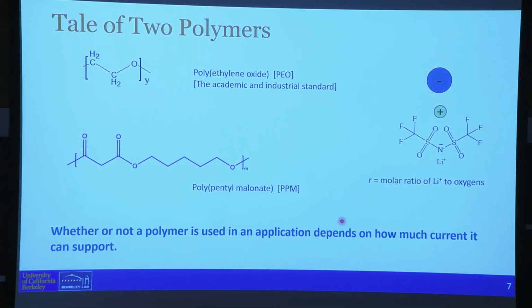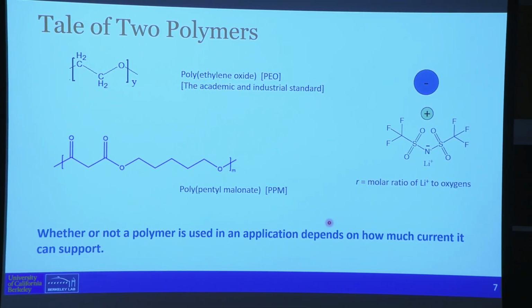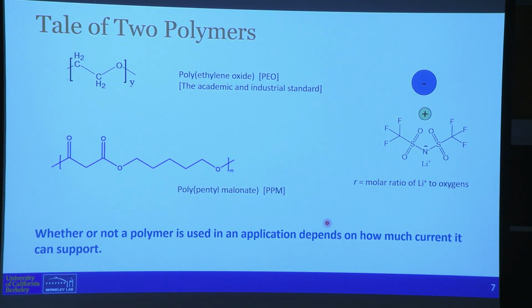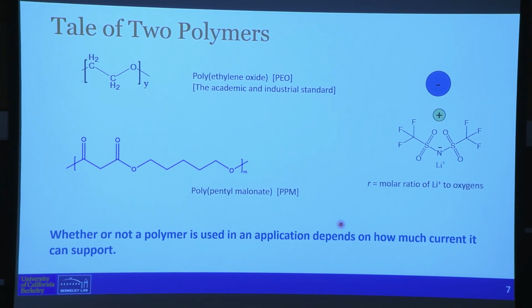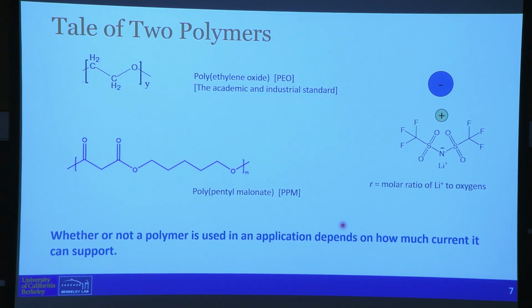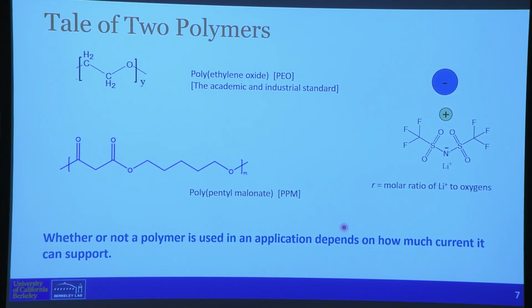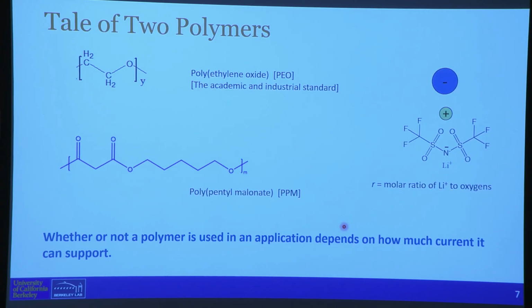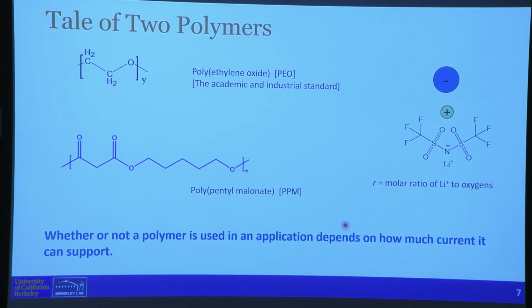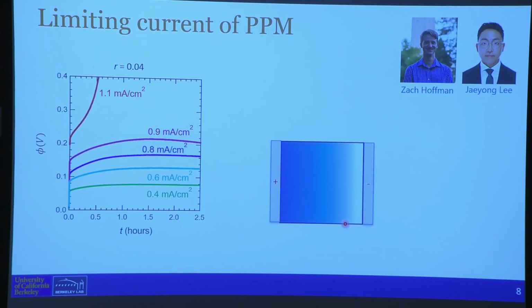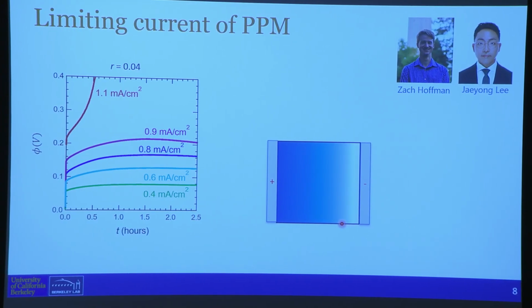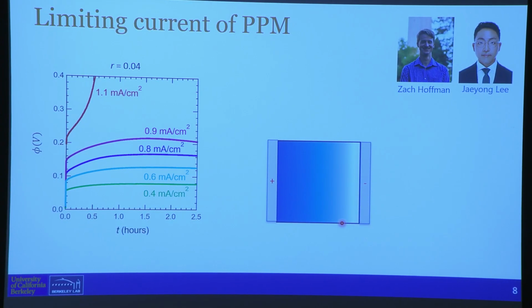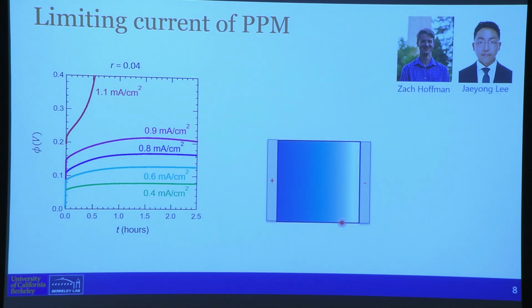And most of the time I will be using R as a measure of concentration, which is the moles of lithium per oxygen. And it's just convenient for both polymers. Both polymers have oxygens. I'm not showing the hydrogens. They'll come into play, and so on. So we're going to try and see which of these polymers can carry a higher current. Okay? So when you take this cell and you apply current across it and measure the voltage, this is what you get for PPM. Okay?